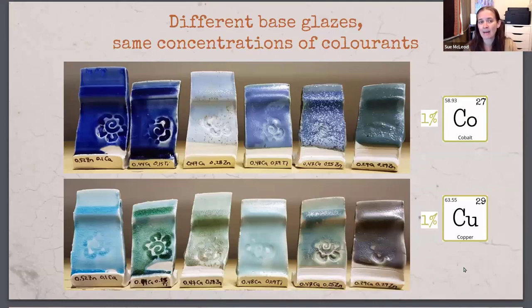And that's based on the chemistry of the base glaze. The chemistry of the base determines the color that your colorant will become. So with cobalt, we can get anywhere from blue, powder blue, we can get purples, we can get greens. With copper, it's usually somewhere between blue and green and a bunch of turquoises in between. This one's kind of gray. That's because there's a bunch of titanium in this glaze. So it all depends on the chemistry of the base glaze, what color that colorant will become.